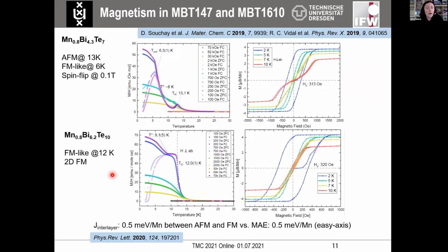Some problems started when we and other groups moved to the characterization of magnetic properties of higher analogues, 1-4-7, 1-6-10, 1-8-13 phases. There it was noticed that the antiferromagnetic transition sets in at a lower temperature. Naturally, you dilute the stacking with the non-magnetic spacers, and the interlayer exchange coupling reduces, so the transition shifts from 24 to about 13 K. This onset of an antiferromagnetic transition is very quickly followed by something that looks like a metamagnetic transition into a ferromagnetic-like phase, so not the hysteresis here. Interestingly, in 1-6-10 compound, there was not even a visible kink corresponding to the antiferromagnetic transition. We almost immediately saw something that looks like a ferromagnet.